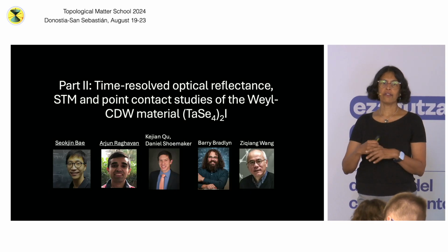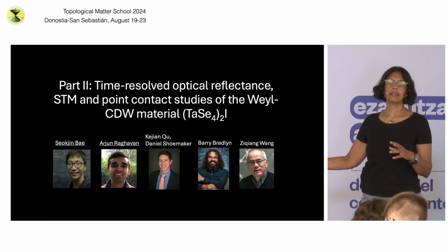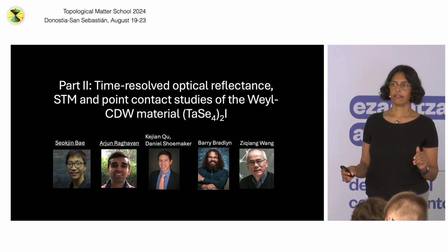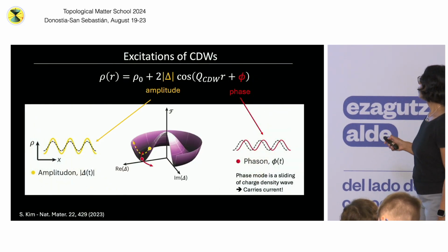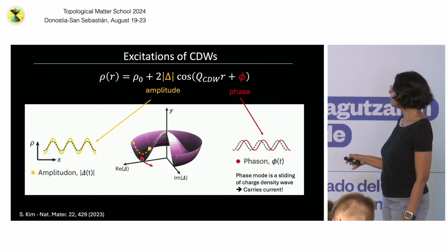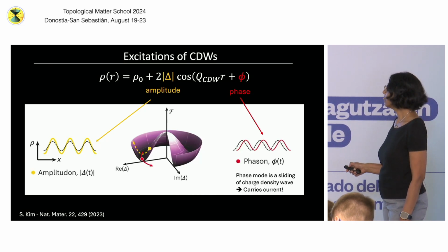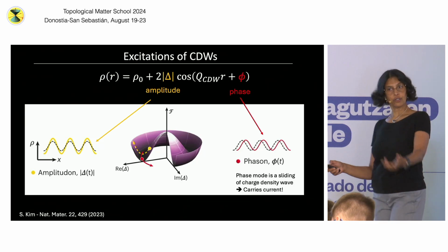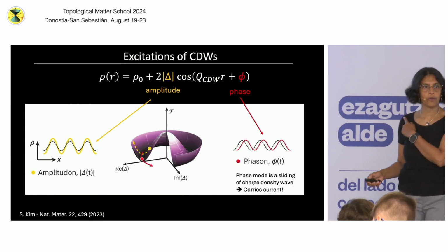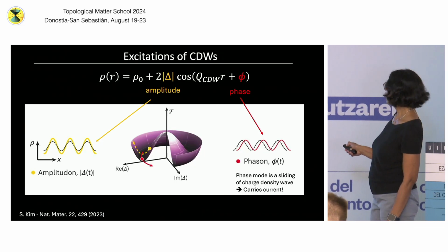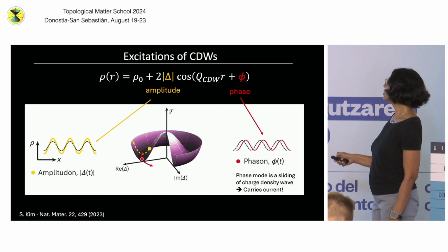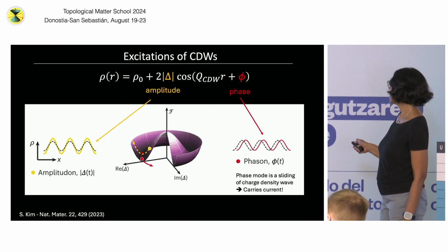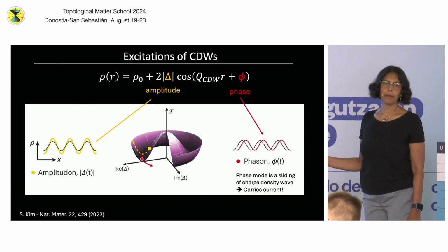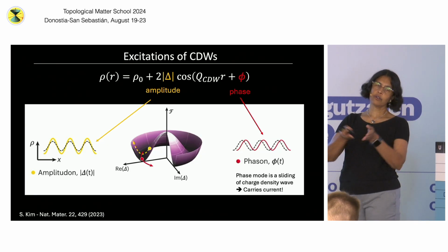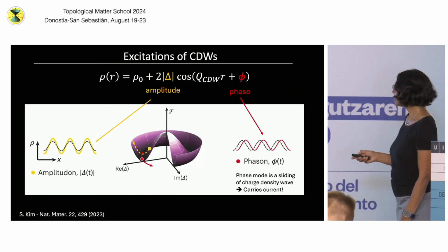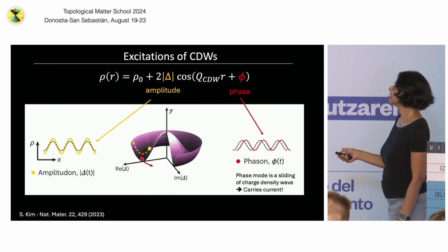The second thing is the charge density wave is a very interesting one. It's a long wavelength, incommensurate 1D charge density wave. If you have a charge density wave, here's your CDW in 1D, then you can have two different kinds of excitations. One is the amplitude going up and down. In fact, you saw examples of that in the previous talk, the amplitude of the CDW changing with light. The other is that the phase of the CDW can slide. Both of these are low energy excitations. This is called the amplitudon, and this is called the phason. The phason usually behaves like sound, like a massless acoustic wave. The amplitudon can have a mass because there's some energy required for this.